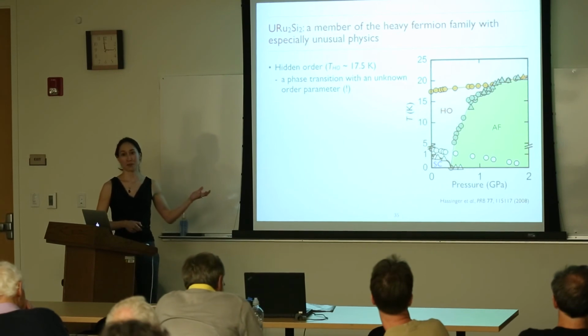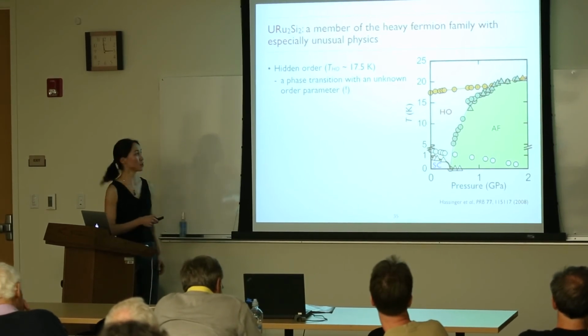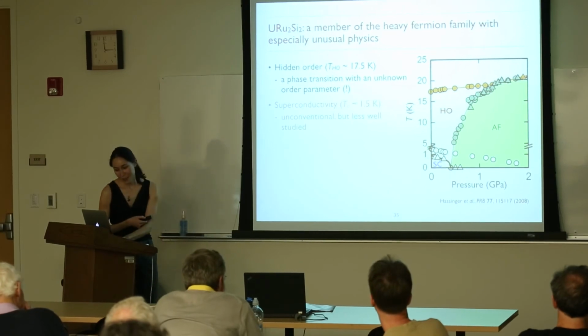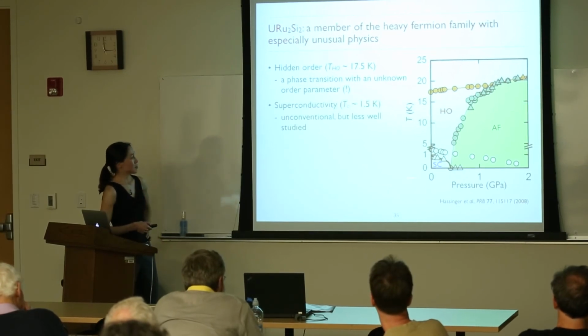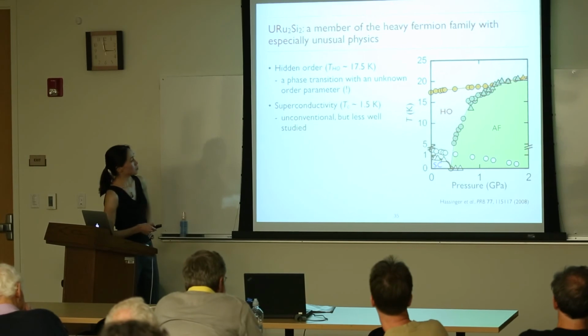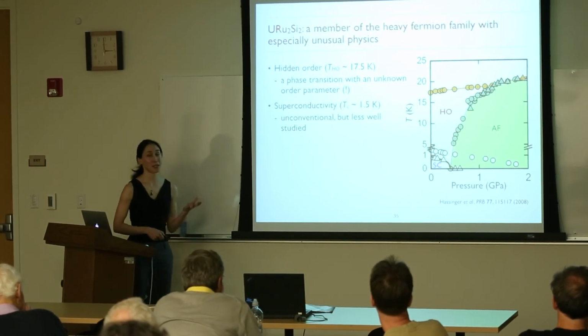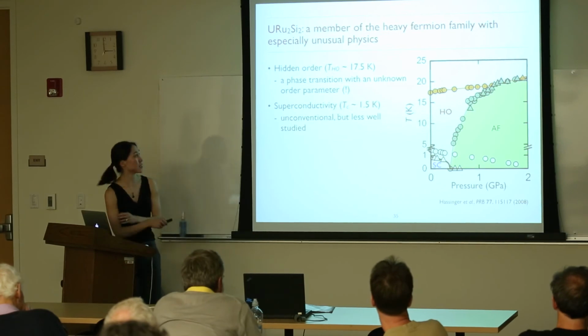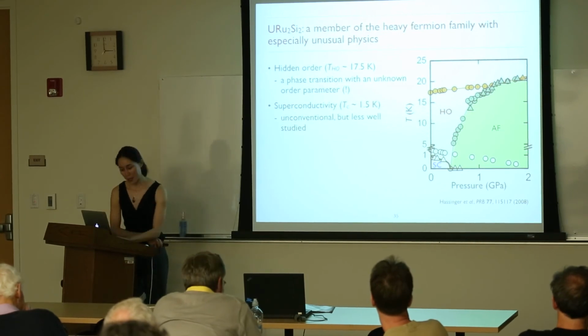But so far, the broken symmetry hasn't been identified. So we don't know what the ordered state is. Hence, this is called the hidden order state. And then within that hidden order state, there is also a small superconducting region below about 1.5 Kelvin. It's believed to be unconventional, but it's not as well studied because the hidden order has perhaps attracted the most attention from people studying this material.